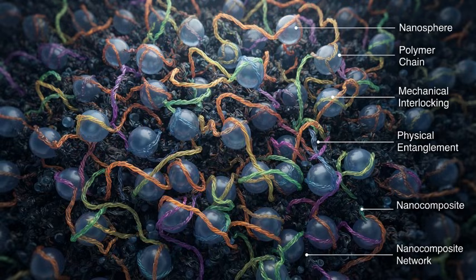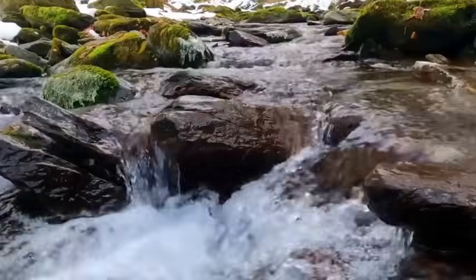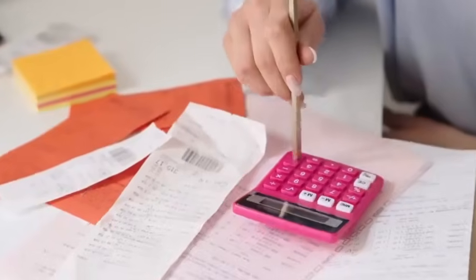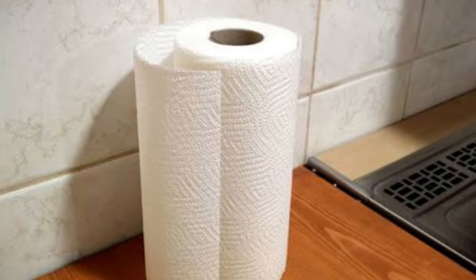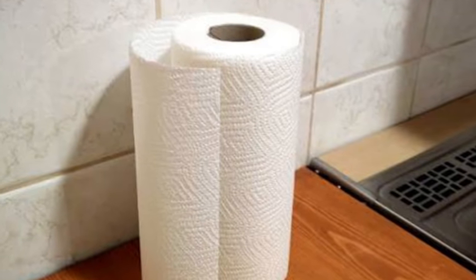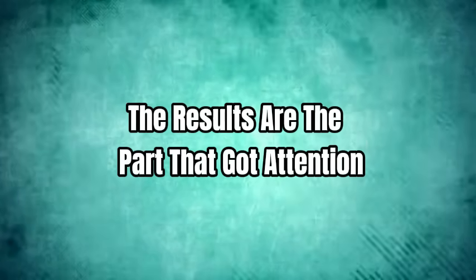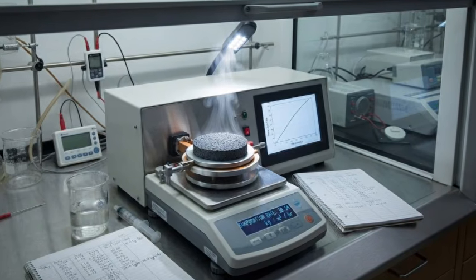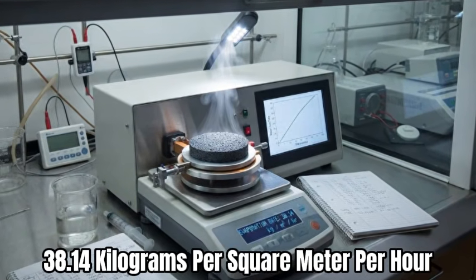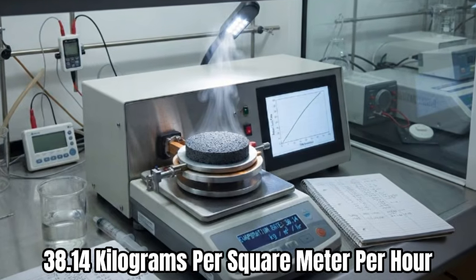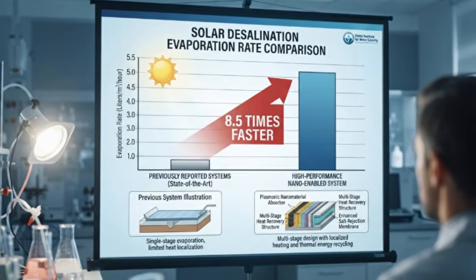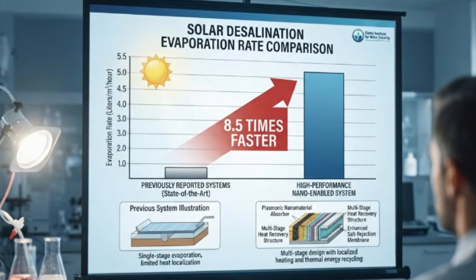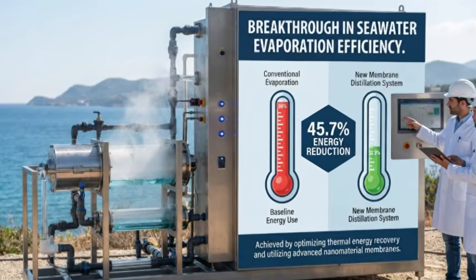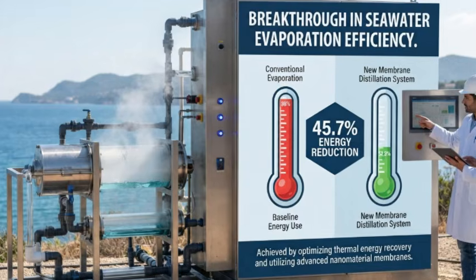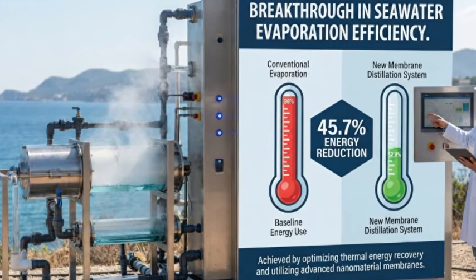And because the nanospheres are physically interlocked by those polymer chains, they can't clump. Water moves up through the structure by capillary action, the same effect that pulls water up a paper towel, so there's no pump anywhere in the system. The results are the part that got attention. The material hit an evaporation rate of 38.14 kilograms per square meter per hour, which is 8.5 times faster than previously reported solar desalination systems. It cut the energy needed to evaporate seawater by 45.7% compared to conventional approaches.